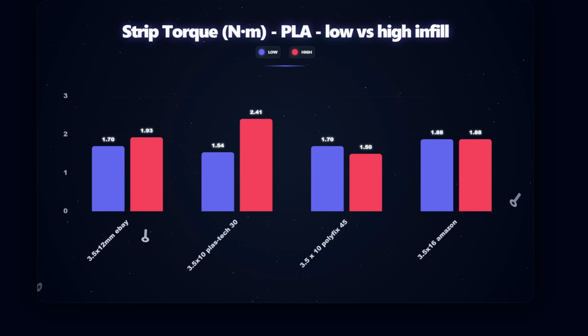Infill type and density probably does matter, but I couldn't really replicate it in tests. Lack of infill is probably more likely to cause a boss to split, but this only happens at abnormal torques or with materials with very poor layer adhesion. And this is probably more important a consideration for parts you expect to be under strain.